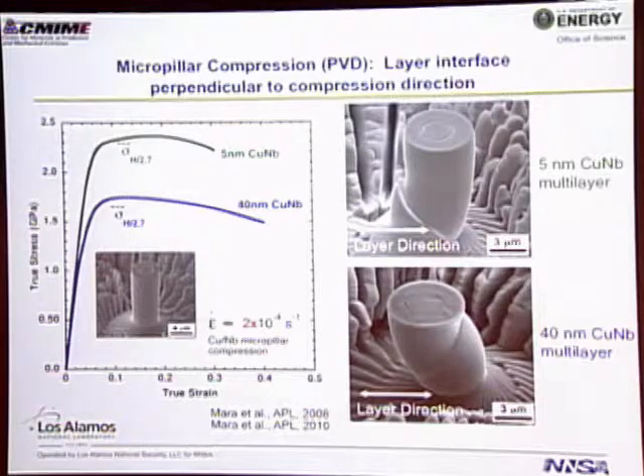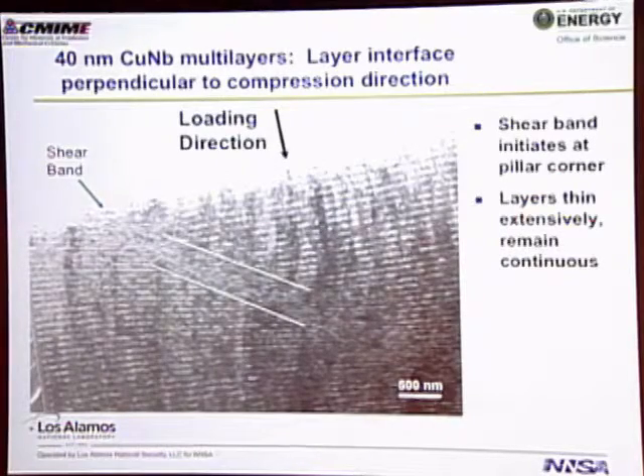Now, one interesting thing that we see here is after we load up the material, what will happen is this band will form, and then the thing becomes softer and softer as we deform it more and more. And you can see that band right here. So the question is, well, why is that band making it softer? Is it just breaking our layers as this band grows? Because our layers are what make it strong, so if you don't have any layers anymore, that would make sense why it would be weak. But the answer is actually, if we section this, we can go in using a focused ion beam, and we can section this into a TEM, or electron microscopy sample. And we can look at the structure of this band.